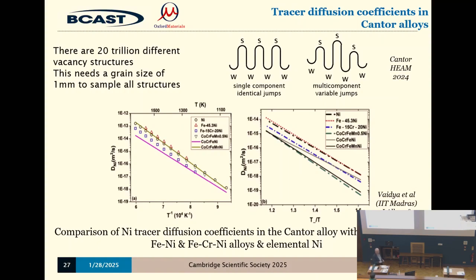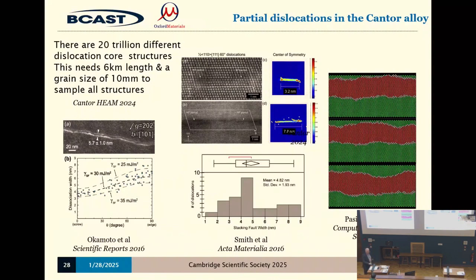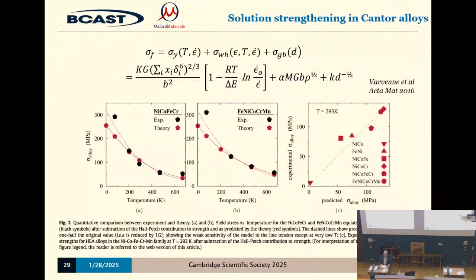Going on to what about the mechanical properties we talked about? Well, the mechanical properties depend upon not vacancies, which is a point defect in a crystal, but something called dislocations, which I'm not going to try and explain in any way, but this is a dislocation in a face-centered cubic multi-component material, and the dislocations are lines of a defect in the crystal structure, and the reason face-centered cubic metals are so soft is because they move, and that causes the planes to roll over each other very easily. You don't need to know the details of it, but these dislocations don't move so easily. I'm running out of, oh no, there it is. You can see they're sort of very wiggly, and that's because of those local strains. So you do get the shapeability, you do get the fracture resistance, but it all happens at a much higher strength, which is why they've got such good properties.